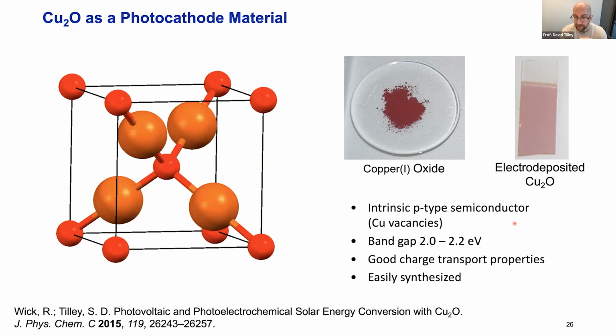What this means is, with water splitting systems, the solar to hydrogen efficiency is directly related to the current, which is directly related to the light absorption. So we can essentially calculate the maximum solar to hydrogen efficiency of this material just with the light absorption. With that number, you get to 18%, I believe, if you were to get every photon more energetic than the band gap. So just to give you an upper bound, we could easily hit the 10%, let's say.